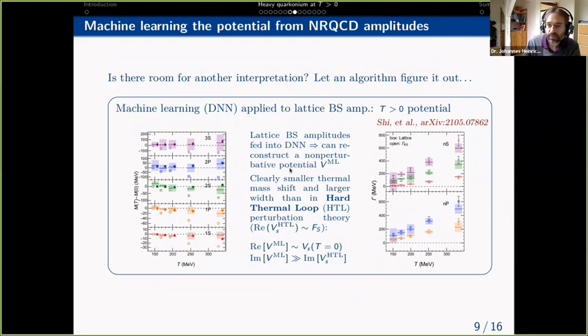We can also let an algorithm figure out what is going on. So people used these Bethe-Salpeter amplitudes, stuck them into a deep neural network, and let machine learning figure out what is coming out. And that's what you see in this work by Shi et al. These boxes are the lattice results for the mass shifts of the different states that you see here. The open circles down here are the leading order hard thermal loop predictions for the mass shifts, and the filled symbols are what you get out from the deep neural network. So the deep neural network reproduces essentially the results that the lattice had obtained for the energies when you give it the Bethe-Salpeter amplitudes.